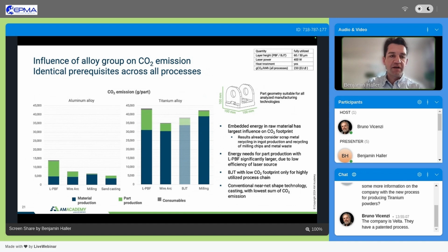For wire arc DED, it's not as extreme. The material is already bigger. But when we look at titanium, the CO2 emissions are much, much higher during the raw material extraction already, so the printing itself has a much lower impact. So this makes the optimization of the printing process that we come to later much more important for laser powder bed fusion of aluminum as compared to titanium.